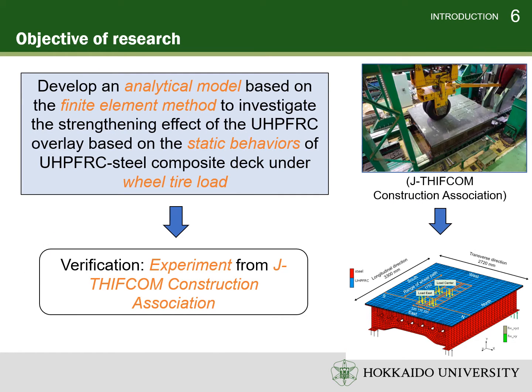In this study, a nonlinear finite element analysis is performed using the commercial FEM software MSC Marc to simulate the steel bridge deck with and without the UHPFRC overlay under static wheel load. The strengthening effect of the UHPFRC overlay is investigated based on the deflection of the steel deck in both longitudinal and transverse directions and the deformations at positions under severe stress concentration. The analytical results are compared with those from the experiment of wheel load acting on the steel deck with the UHPFRC overlay that was conducted by the J-THIFCOM Construction Association.